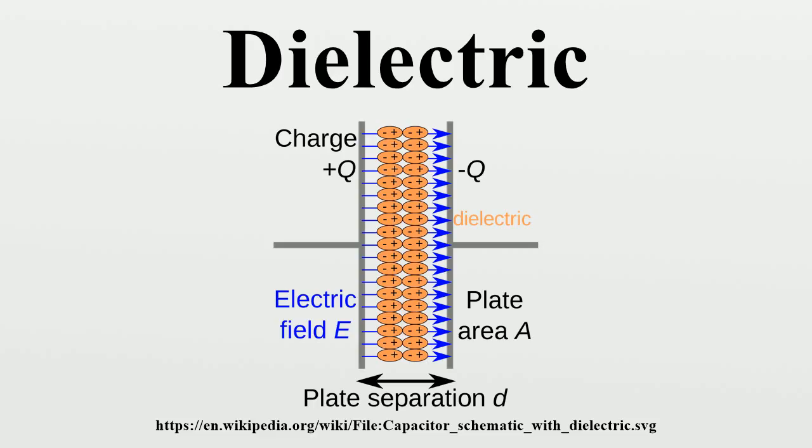Tunability. Tunable dielectrics are insulators whose ability to store electrical charge changes when a voltage is applied. Generally, strontium titanate is used for devices operating at low temperatures, while barium-strontium titanate substitutes for room temperature devices. Other potential materials include microwave dielectrics and carbon nanotube composites. In 2013, multi-sheet layers of strontium titanate interleaved with single layers of strontium oxide produced a dielectric capable of operating at up to 125 GHz. The material was created via molecular beam epitaxy.